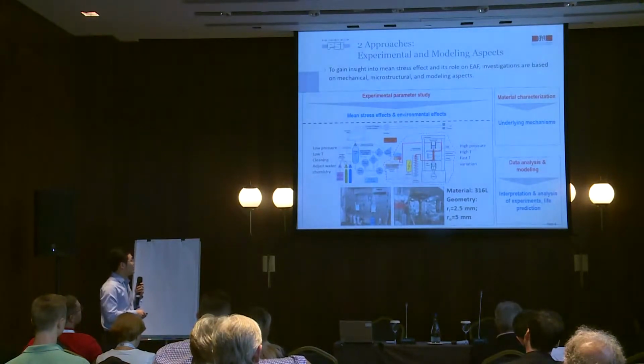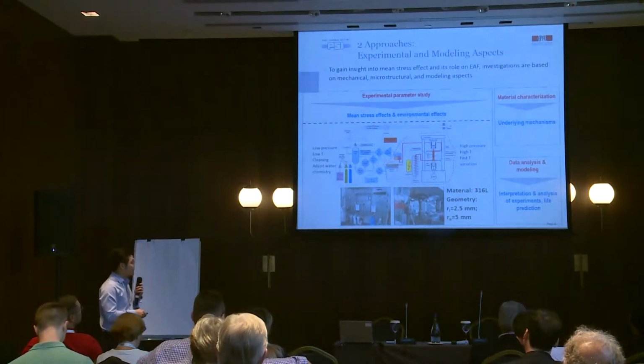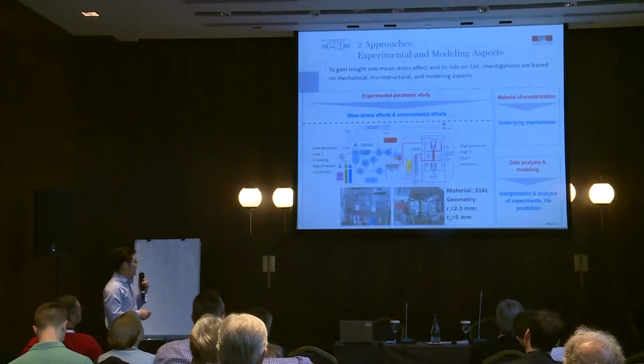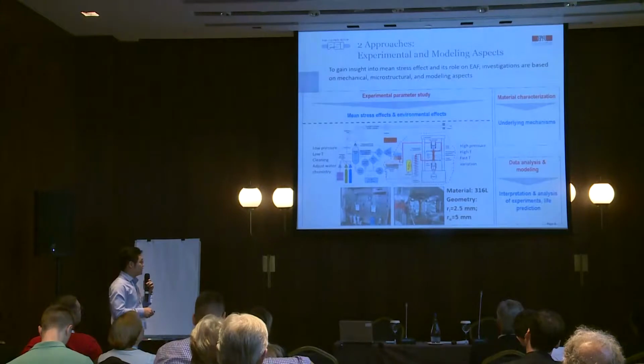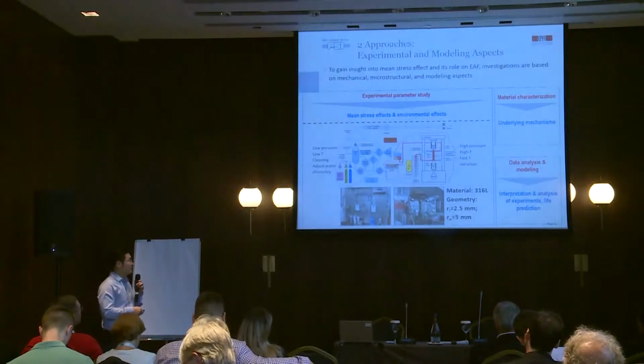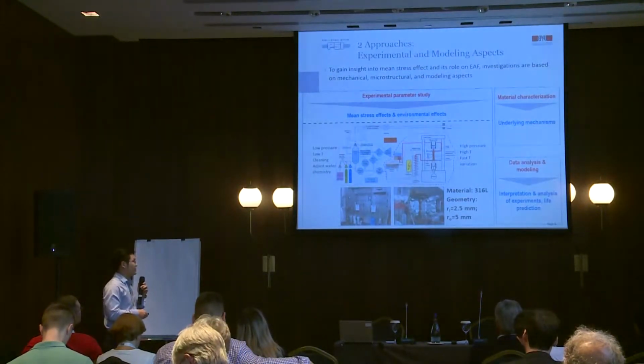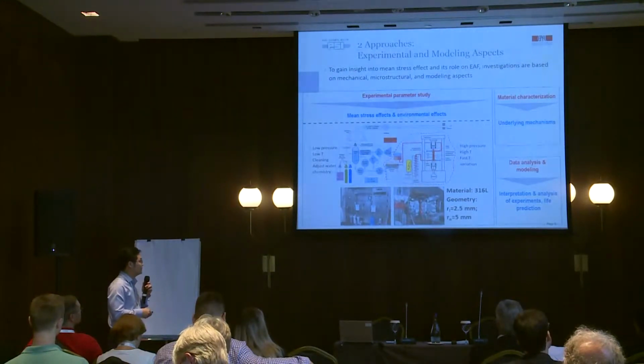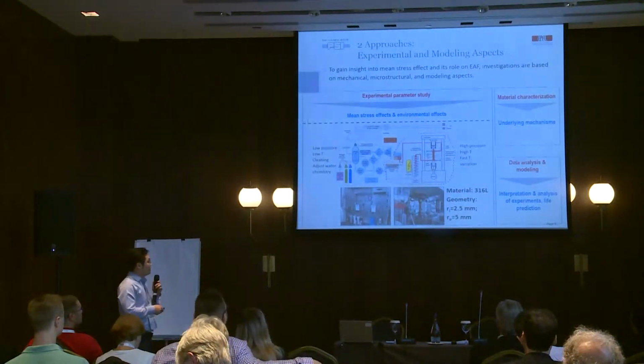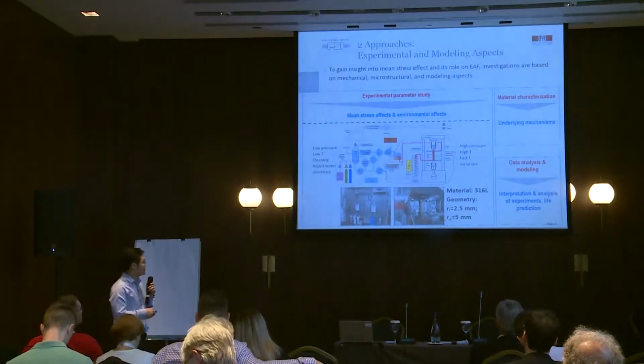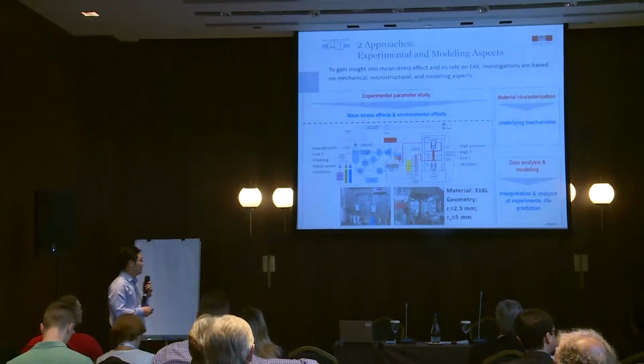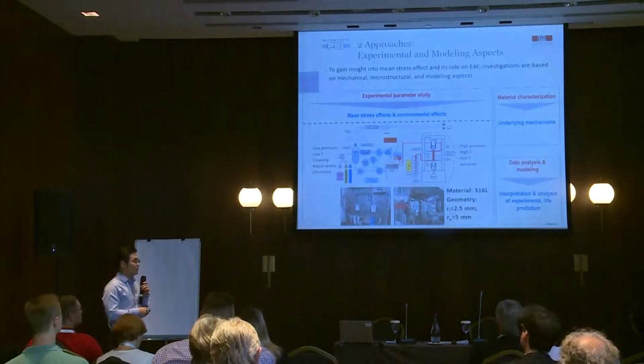Here is the high temperature. The material applied is 316L austenitic stainless steel, and a standard cylindrical hollow specimen with a geometry of 2.5 millimeter inner radius and 5 mm outer radius was applied. The specimen was heated from the inner side by the high temperature water, and the strain signal is measured by the extensometer attached on the specimen surface. A sinusoidal waveform with frequency 0.17 Hertz is applied, and most of the tests are under load control.